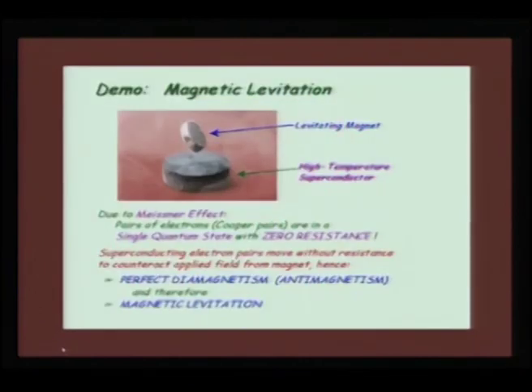So, if the sample is in a levitated or diamagnetic situation, one of the most important manifestations is that it can actually lift up a magnet. In this cartoon you would see this, and the next cartoon animation will help you understand it. If there is magnetic levitation, it is actually due to the Meissner effect, where the pairs of electrons are in a single quantum state with zero resistance.